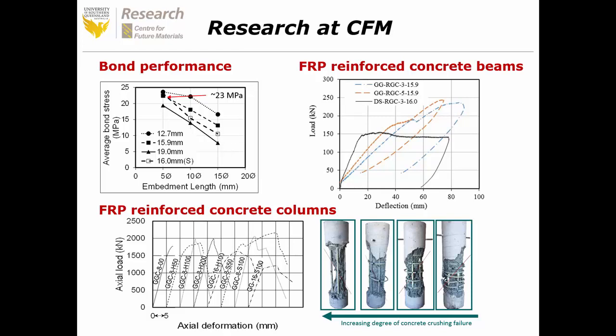And also, by providing sufficient spiral reinforcement to our concrete columns, we can minimize the degree of concrete crushing in our column members. And similar to beams, we can achieve a pseudoductile failure behavior in our concrete columns. And again, this is very important because FRP bars are perceived to fail in a brittle manner. But if we can design them effectively, we can achieve higher strength concrete elements, but also with a pseudoductile failure behavior.